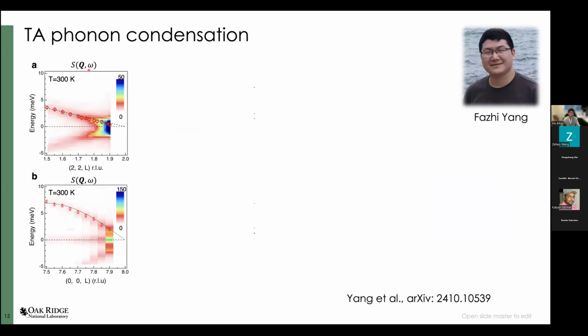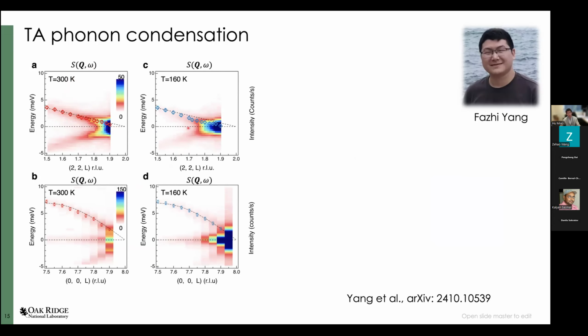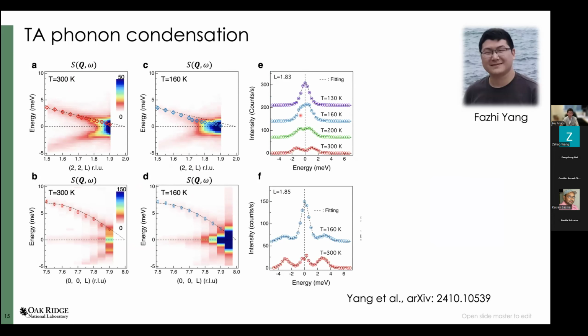Finally, we want to really justify that it's transverse by measuring the phonon dynamics. Here shows the transverse acoustic phonon dispersion at room temperature, and panel B shows the longitudinal acoustic phonon dispersion at room temperature. And this panel shows the dispersion slightly above the CDW transition temperature, and we can observe the softening of the transverse phonon, but the longitudinal phonon doesn't really change. Here shows the IXS spectrum, where we can clearly see the softening of the transverse acoustic phonon, and there's not much change on the longitudinal acoustic phonon.